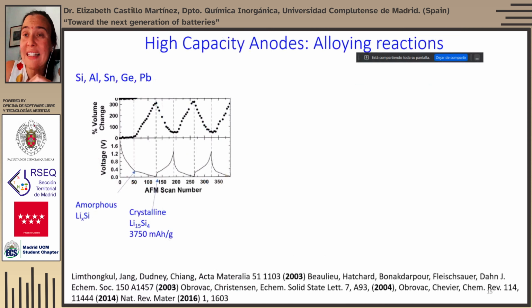On the anode side, there have been lots of reports as well on trying to use high-capacity anodes. Remember that graphite has about 370 milliamp hours per gram based on the insertion of 1 lithium ion per 6 carbon atoms. But when lithium reacts with p-block elements like silicon, aluminum, tin, germanium, lead, it can react through alloying reactions, which can give much higher capacities. For example, in the case of silicon, it can form Li15Si4, which has a capacity which is 10 times